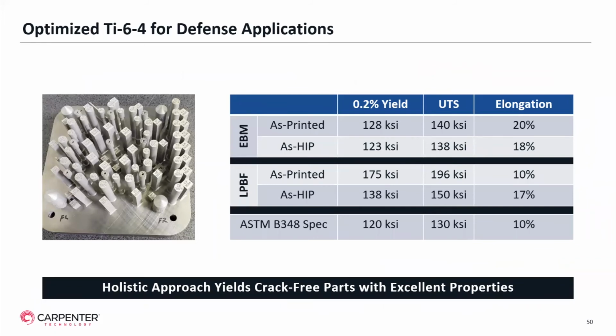So this is just some example properties that we've achieved out of this holistic approach, looking at everything to be able to get the right properties. Either from electron beam or laser powder bed fusion, whether as printed, stress relieved, heat treated, or HIPed, we're now able to achieve extremely good mechanical properties, which are meeting normal industrial specifications for Ti-64. And again, we can make complex components with, I would say, at least a vastly reduced probability of cracking, if not eliminated in many cases. And again, how do we do that? It's the holistic approach, understanding the entire process chain, the heat treatment, how to specify the powder, and so on.